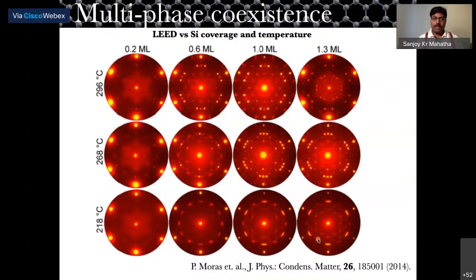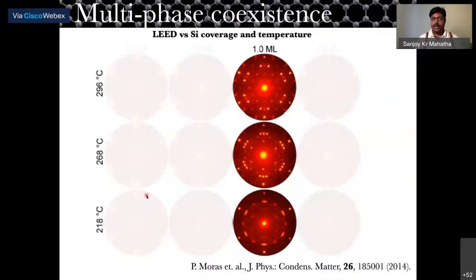Okay, so you can see these are different monolayers. Monolayer means when it is covering the whole surface of silver, and they are grown at different temperatures: 296, 280, 268, and 218. Let's concentrate on one monolayer at different temperatures. At the lower temperature, 218, we see a very strong intensity from 4 by 4, and there are some signatures of root 13 by root 13, right?